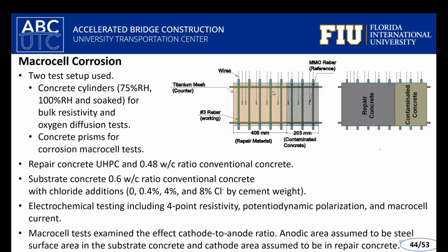Part of this has to do with what we call a halo effect, and it is also representative of what we call macrocell corrosion. You have steel that's embedded in the new material, and you have some rebar that's still embedded in the substrate material, and invariably some amount of chlorides remains in the system. So we look at the effect of coupling this steel embedded in different environments and see if it can be adverse, and if UHPC repair work can be any different or better, for example. Of course, the caveat is the extent of the repair, but it really depends on the project. Sometimes the repair may be localized, sometimes the repair can be much more. The repair may be a jacket of the whole entire column, for example, covering a greater surface.